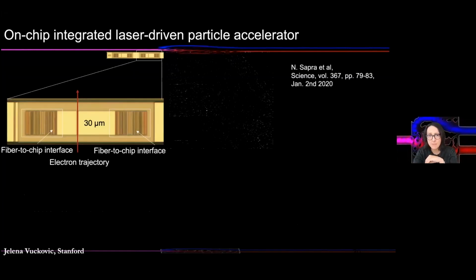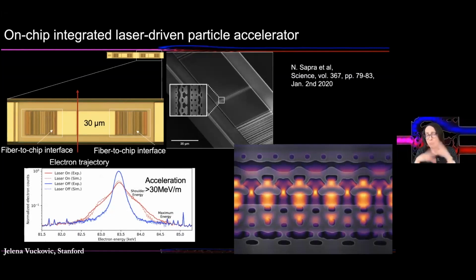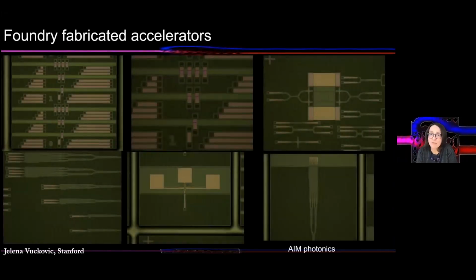So here is the experiment, the whole chip. When we couple electrons from a converted scanning electron microscope with energy of 83.4 kiloelectron volts, if the laser is off, they just exit with the same energy. If the laser is on, they get a kick of 1 kiloelectron volt per 30 micrometers, and they're accelerated with this target acceleration gradient. So if you put 100 or 1,000 of these, by the time they exit this inch of a chip, they would have energy of megaelectron volts, and that could already be very useful for a variety of applications.